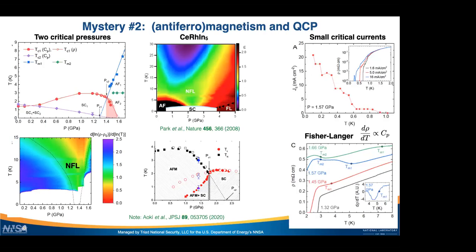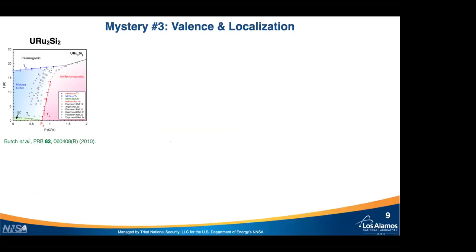But this is very complicated now, right? Because we had this idea that this system is close to a ferromagnetic instability, is a spin triplet superconductor, just like UGe2, URhGe. But that doesn't seem to be quite the case. And actually, this reminds me more of URu2Si2, which is an antiferromagnetic or close to an antiferromagnetic transition. And again, CeRhIn5, which is also close to an antiferromagnetic instability.